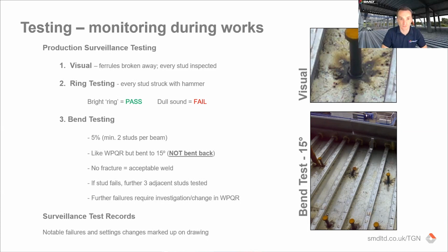So bend testing for production surveillance is only to 15 degrees, not the 30 for the WPQR. At 15 degrees bent, you then leave the stud in that position. You do not bend it back, because obviously that's just creating extra force on the weld, and ultimately the 15-degree bend isn't reducing the height of the stud that much in terms of its geometry. So you can just see an example here of a welded, bend tested stud. If you get no fracture on bend, that's an acceptable weld.